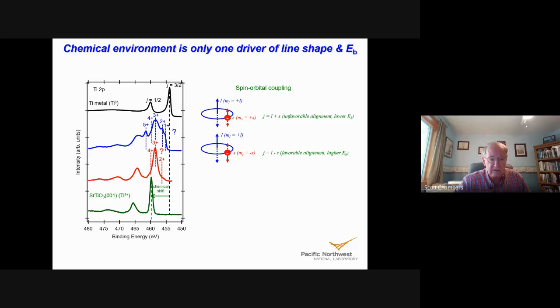Well, if that's what you did, you would be completely wrong, because the blue spectrum is from an ultra-high vacuum cleaved single crystal of Ti2O3. It has 100% titanium 3 plus. The red spectrum is from an epitaxial film of lanthanum titanate, grown in situ with the photoemission chamber, in this case over in Germany at BESSY. This also has nothing but titanium 3 plus, but the spectra are completely different.